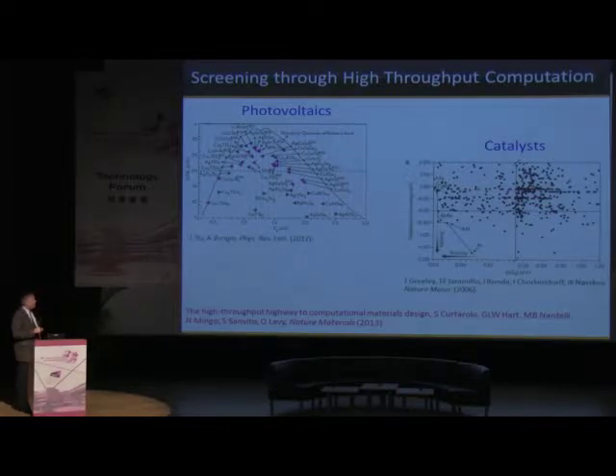A similar example over here is in catalysis. Here they're looking at the hydrogen evolution reaction, a catalyst for that, and they're looking at binary alloy catalysts. And they're plotting two different discriminators. I'm using this term discriminator, which basically means a property which helps you predict the performance. One is the binding energy of hydrogen on the surface, and the other is a stabilization free energy, which is how thermodynamically stable this material is.